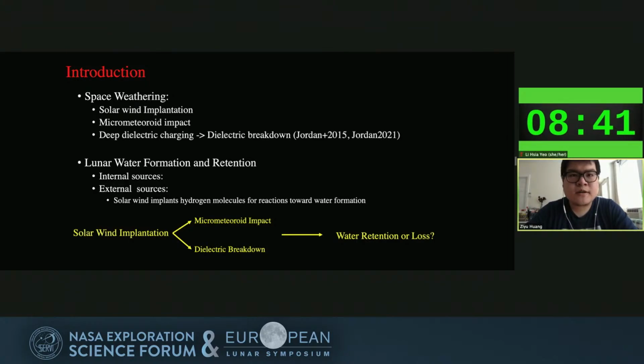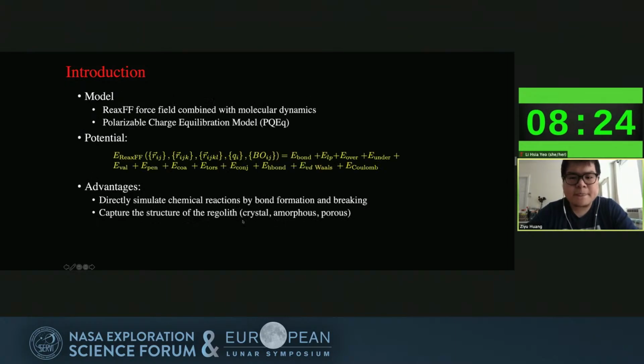Well, micrometeor impact and dielectric breakdown could possibly provide enough energy, but they could also provide too much energy, which can make the surface lose water. So in this way, we use atomic scale simulation to evaluate the contribution of each process. The model we use is a reactive force field coupled with molecular dynamics simulation, and also a polarizable charge